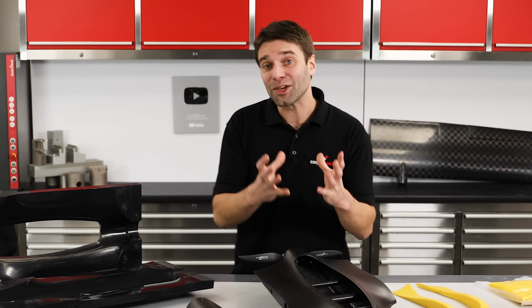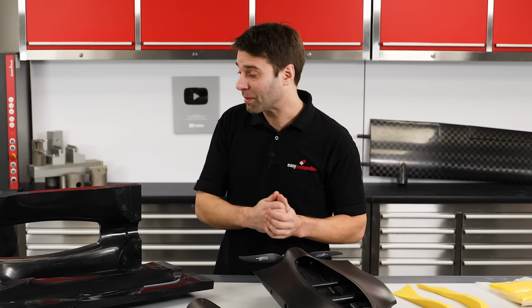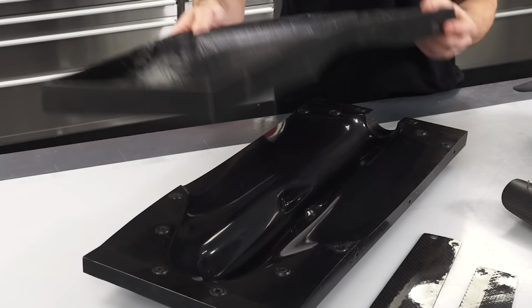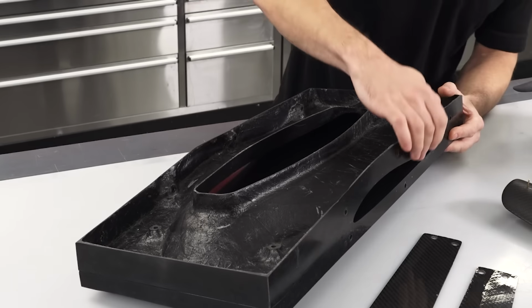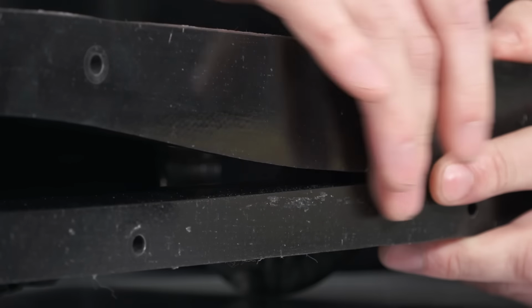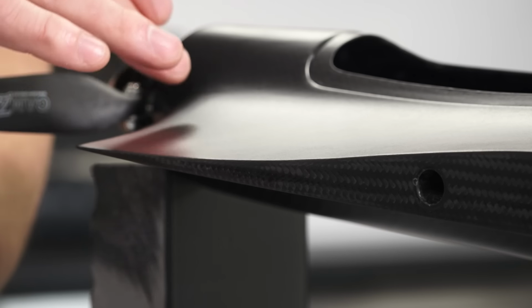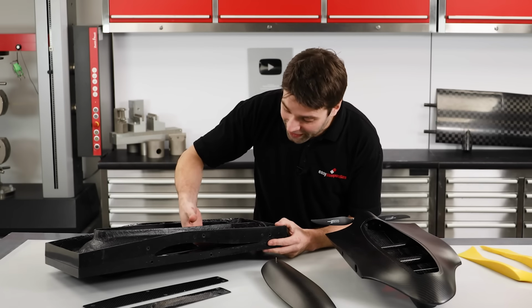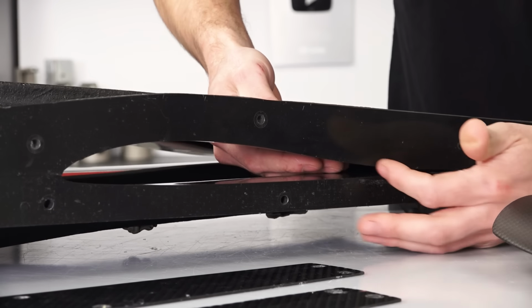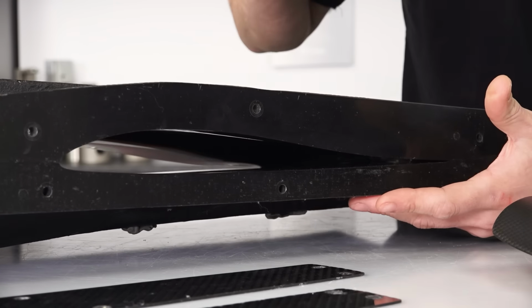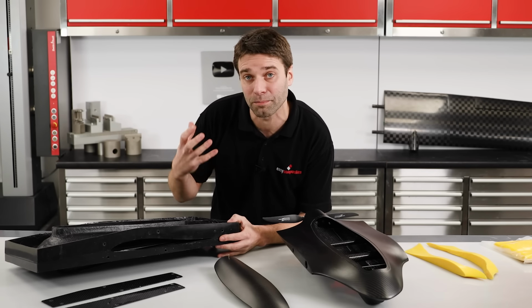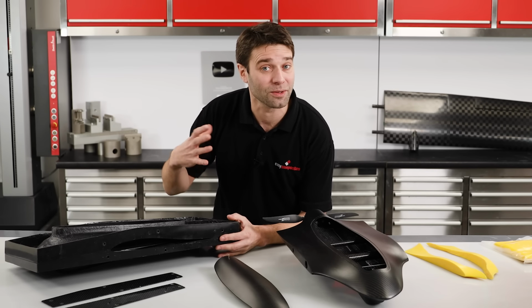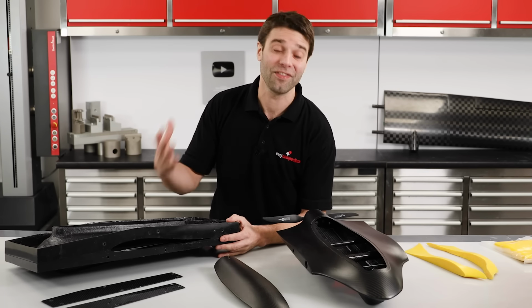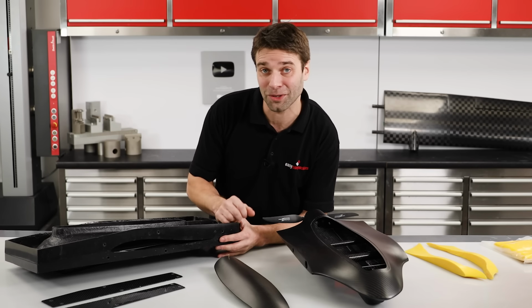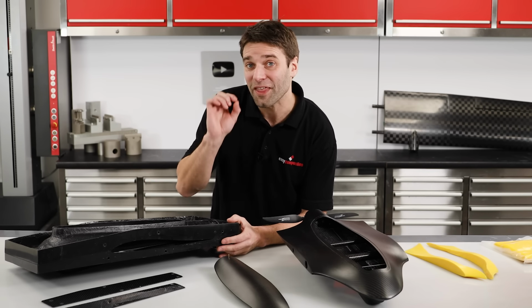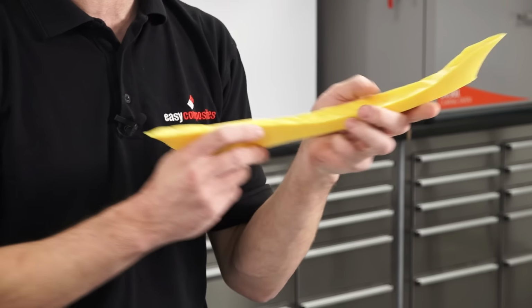But vacuum bagging and curing this in one piece could be problematic. If we look at how these moulds come together, we're left with a very sharp, fine detail that forms the trailing edge here. And if you imagine trying to vacuum bag down into here, it's going to be very difficult, if not impossible, to get that bag to conform without bridging. And if you have bridging, you're going to have a lack of consolidation, and that's going to lead to pinholes on your part. Fortunately though, there is a solution, and it's these.